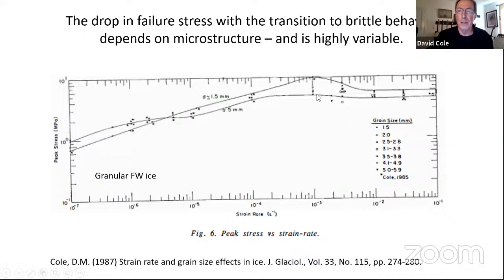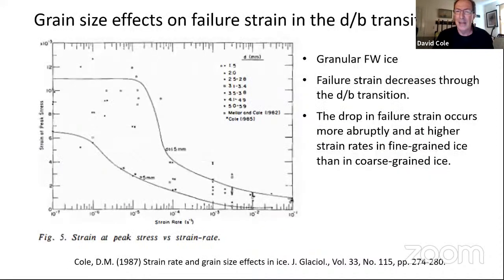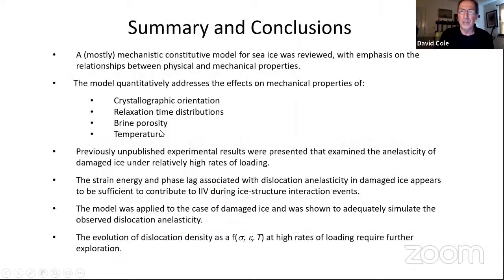Also, some of my own work from the late 80s. If you test fine grain material, you see that drop off, peak strength versus strain rate. But you go up to 5 millimeter grain size, uniaxial compression, and that pretty much goes away. So the strains at failure reflect this same business. The large grain samples start their transition to brittle behavior much more gradually and at much lower strain rates than fine grain material. So it's just a really highly variable process.